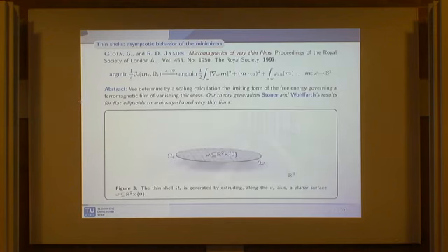So the first result in this direction is the result of Gioia and James, in which they take into account the case of a planar shell. You take a 2D domain, you extrude along the e_z direction, and you want to understand the 2D limit as you shrink this planar shell. They found that your magnetostatic self-energy, which was nonlocal, now at the leading order becomes a local term, so that the magnetization tends to favor in-plane configurations.